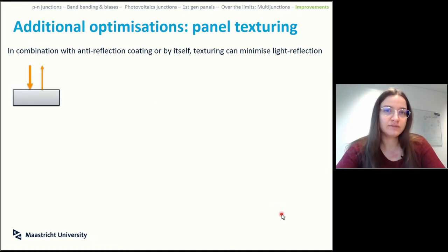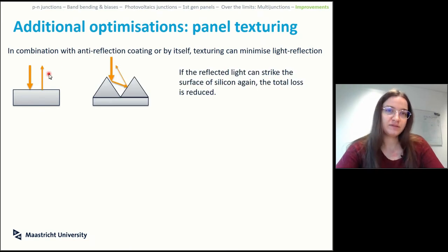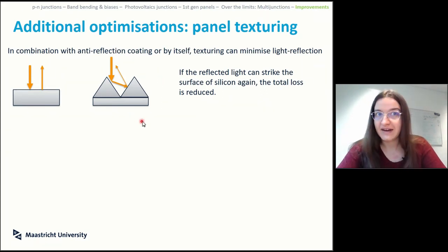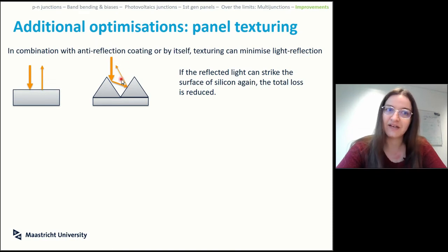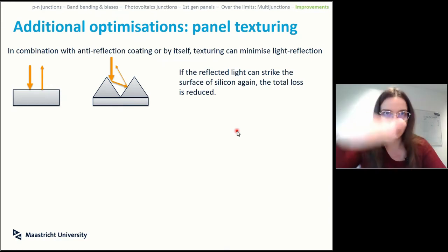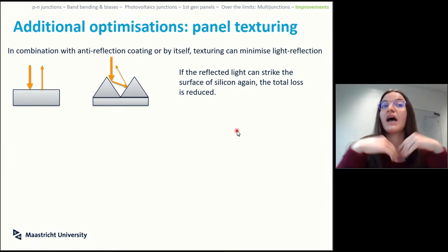Going through the concept of reflections, in combination with this anti-reflecting coating, you might want to think about how you texture your solar panel, because your issue is that if your solar panel is perfectly flat, even if you have incident light at 90 degrees, which is optimal, you still reflect off a certain percentage. But if you have a texture in your surface, you get incidence, part absorption, part reflection. The reflected part will still get another layer of the material to hit, and then another part will get partially reflected, but it will be significantly lower than with a flat surface. So if you manage to texture, you have more surface available to interact with light and make sure that all the light available gets into the material and not out of it.